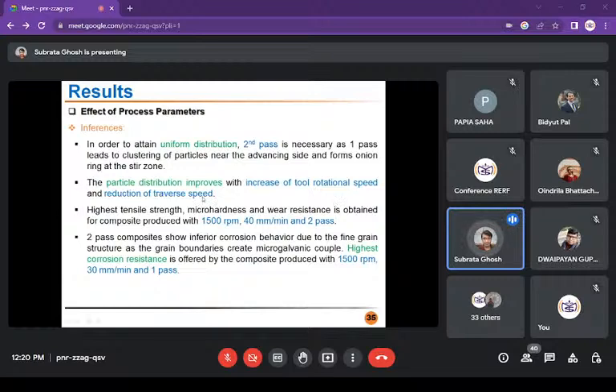So the inferences: the effect of the process parameters, basically the second pass, is very important here. It plays a very good role and offers a good distribution of the reinforcement particles in order to attain your main goal, to succeed in developing this kind of composite materials with the help of the friction stir processing technique. The particle distribution improves with an increase of tool rotational speed and a reduction of the traverse speed. The highest tensile strength, microhardness and wear resistance are obtained for the composite at 1500 rpm and 40 millimeter per minute, for the second pass.